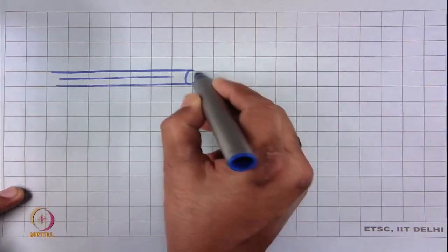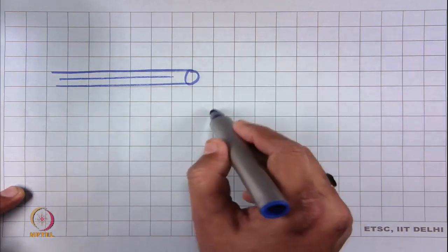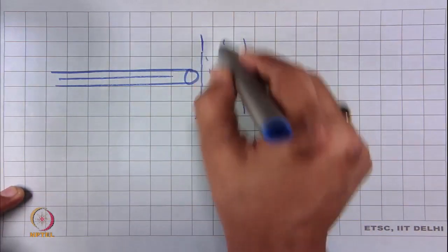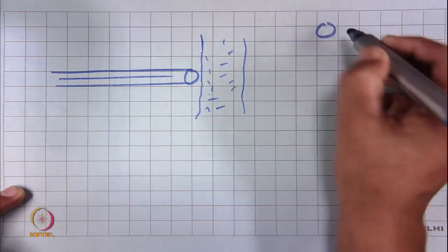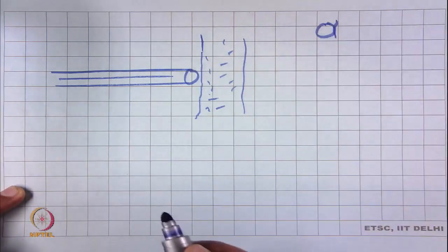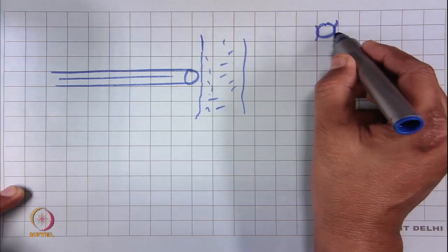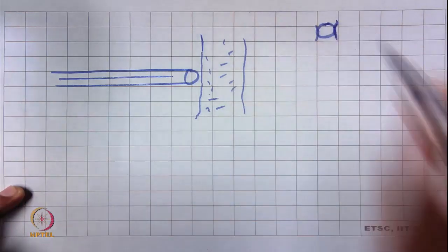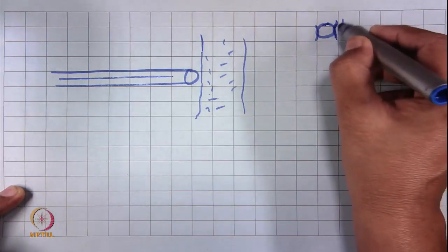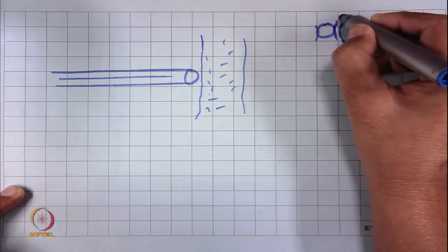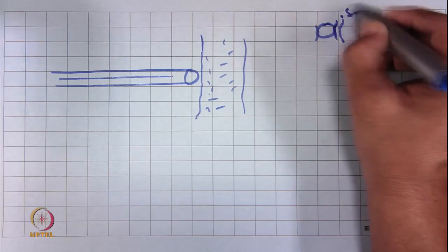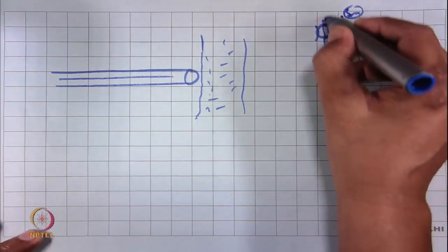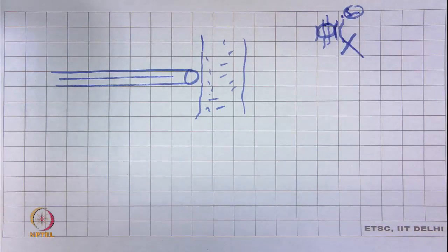Suppose this is the beam, the beam of light cross section, and there is a flow at right angle, with fibers moving with the slurry. There will be a few fibers which are not crossing completely but only partially. They also scatter light, but in lesser quantity. That will give a wrong result, showing as if the fiber is smaller in diameter. So that fiber we have to discard, and only fibers which cross completely we have to take. Now, there is a technique that I will explain.